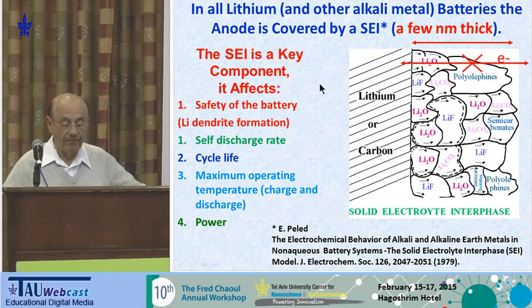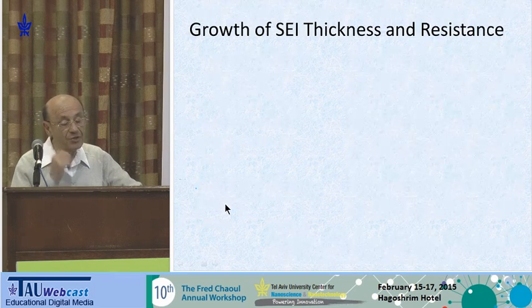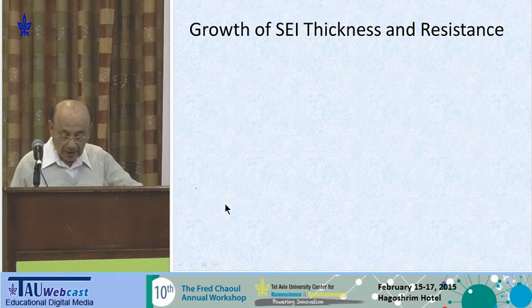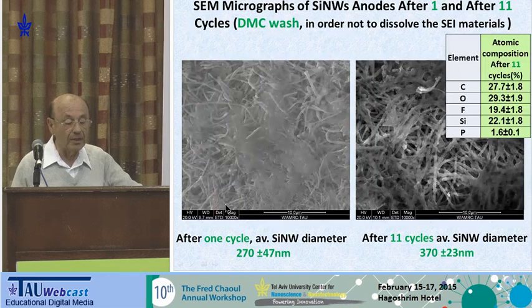It can't function. So this model was published in 1979, and today all the experts in this field are using this model to analyze their results regarding lithium batteries. So the SEI is a key component to affect safety, self-discharge, cycle life, operating temperature, and power. Therefore, we study the growth of SEI and its resistance on the silicon nanowires.